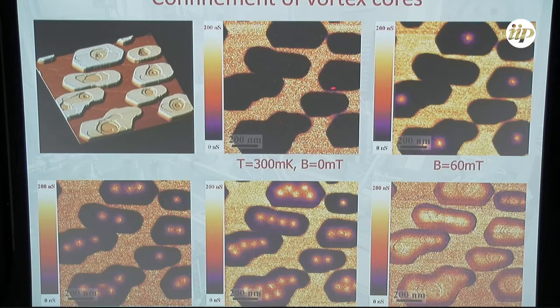These islands are superconducting, so now I take a collection of islands and put a magnetic field. First, without magnetic field, I can do tunneling spectroscopy. Here the color corresponds to the existence or not of the superconducting gap. So black color is a superconducting gap. You see immediately that all islands are superconducting. You see also that this wetting layer of amorphous lead is not superconducting. And then if you raise the magnetic field, you see Abrikosov vortices entering into the sample, producing Abrikosov clusters or chains, and you can even go to the HC3 regime of superconductivity, where only the superconductivity at edges exists.